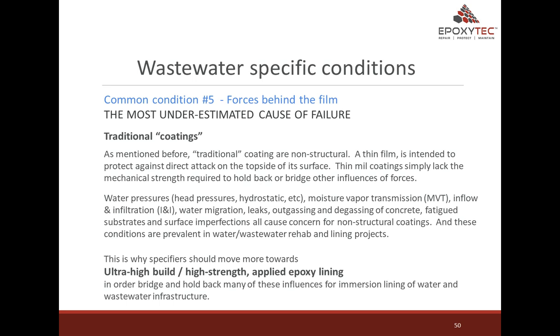Common condition number 5, forces behind the film. This is the most underestimated cause of failure. Traditional coatings. As mentioned before, traditional coatings are non-structural. A thin film is intended to protect against direct attack on the top side of the surface. Thin mil coatings simply lack the mechanical strength required to hold back or bridge other influences of forces. Water pressures, as in head pressures, hydrostatic, etc., moisture vapor transfer, MVT, inflow and infiltration, I&I, water migration, leaks, outgassing and degassing of concrete, fatigue substrates, and surface imperfection all cause concern for non-structural coatings.